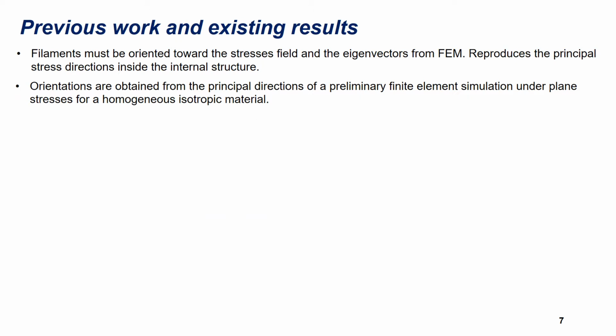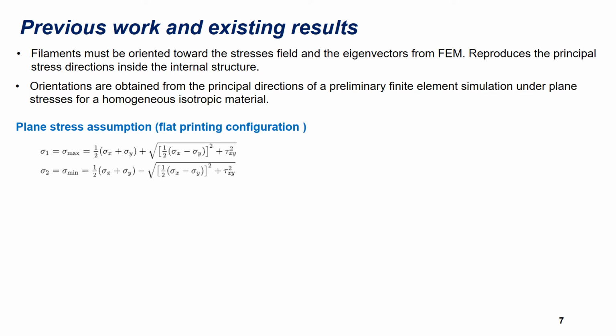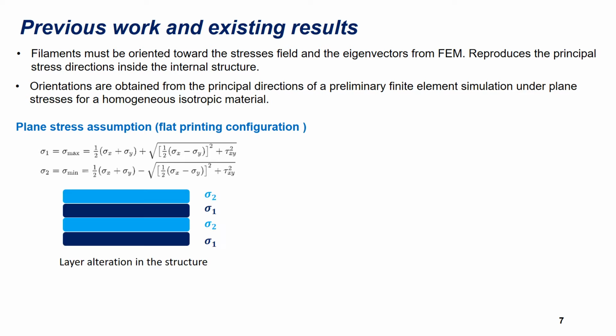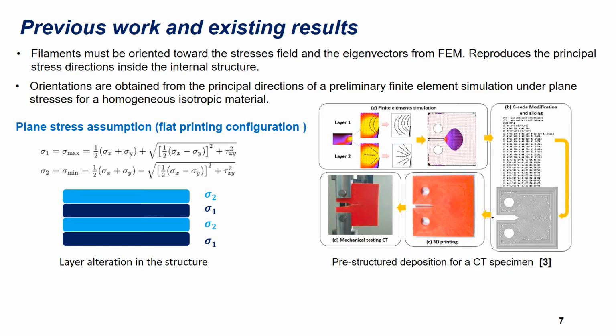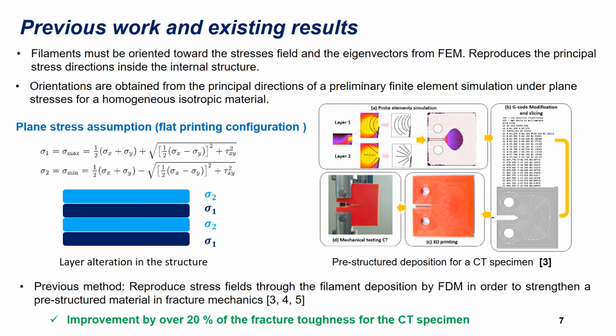An optimized method was developed based on reproducing principal stress directions inside the structure. Those orientations are obtained from the principal directions of a preliminary finite element simulation under plane stresses for a homogeneous isotropic material. Since the filament has only one possible deposition angle, a layer alternation inside the structure is used between both principal orientations. In the region where principal stresses are the highest and mainly tensile, optimized trajectories will be generated. Previous work on a CT specimen proves an improvement of over 20% of the fracture toughness, showing therefore the beneficial effect of such deposition method.